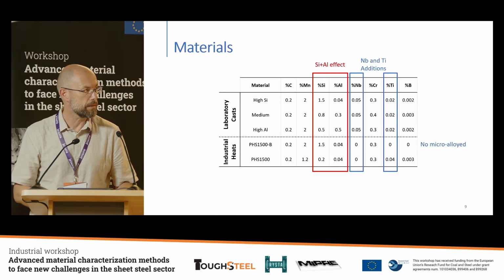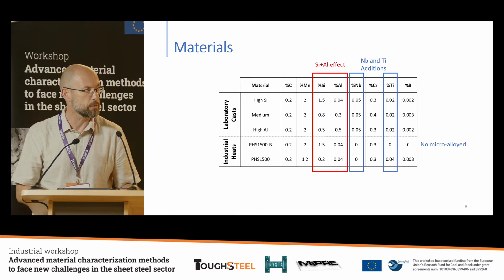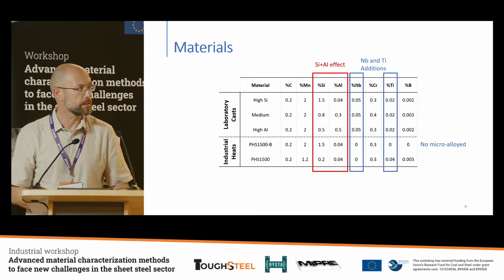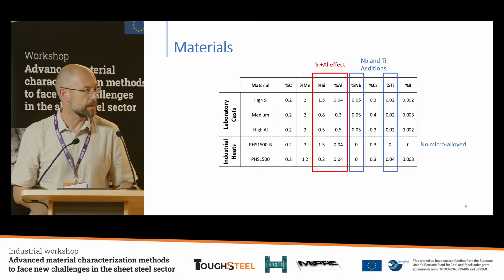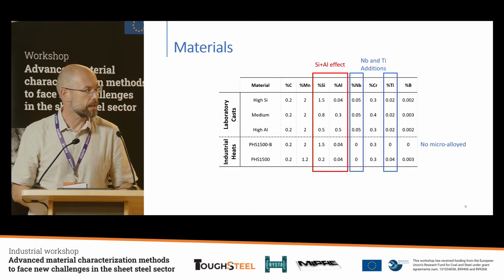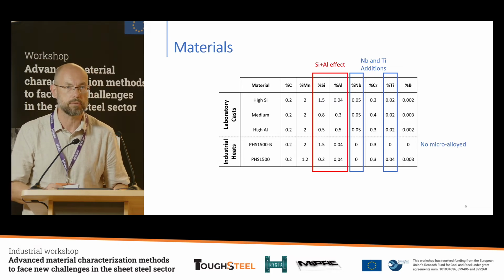But let me summarize which are the aims that we were seeking in that project, and highlight some of the interesting results that we got from my side. My side is the microstructural characterization of the materials that we are using in press hardening. So we were working with industrial heats, which is a PHS 1500 steel, which is very well known. But we also introduced some variations in the silicon and aluminum content in order to see the role of the retained austenite in the microstructure and also in the mechanical behavior.